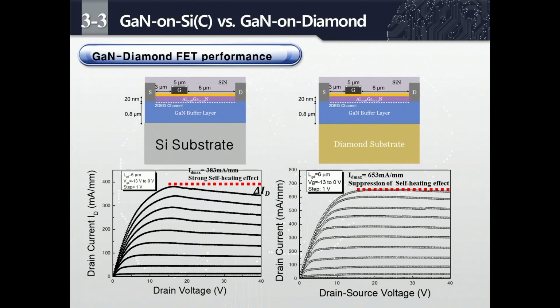So we compared GaN on silicon and GaN on diamond. These two structures have the same epitaxial layers, except for the silicon substrate and the diamond substrate. After fabrication of the device, we measured the output characteristics. One main difference is the drain current level. GaN on diamond has higher drain current compared to GaN on silicon. The other is the suppression of self-heating. GaN on diamond is almost constant, but GaN on silicon has a very strong self-heating effect.